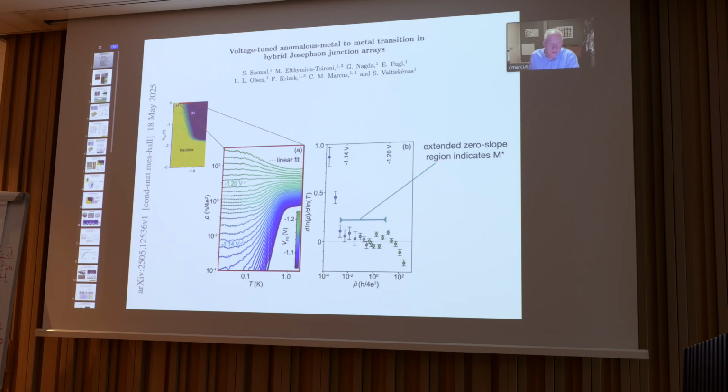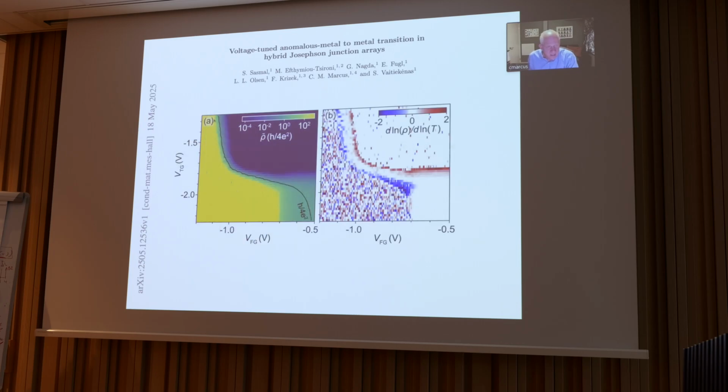But where this gets interesting is by connecting the superconductor anomalous metal insulator transition to the metal that we know lives down here. That line of conductance h over 4e squared goes right through the middle of all of that and now lets us draw a continuous connection between the anomalous metal that divides the superconductor from the insulator from the regular metal where the sides are cut off.